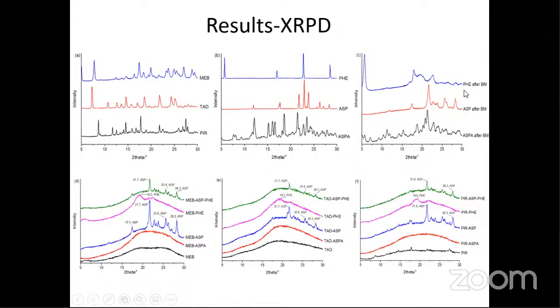And this is a conformer after ball milling. As we can see, the conformers, aspartame, aspartic acid, and phenylalanine, all these three conformers cannot become amorphous by ball milling alone. And here from the D, we can see mebendazole can become amorphous, known by XRD.